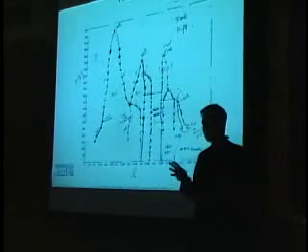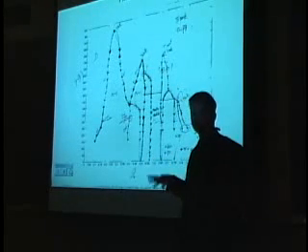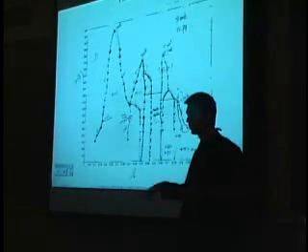When we do Monte Carlo, it's really like a puzzle. In papers, we always show these nicely drawn things, but this is how you get to it. You do an enormous amount of scans in mu, so you scan this way, then you scan in temperature, and you slowly start piecing together which phases exist, where they disappear, how they disappear, first or second order.